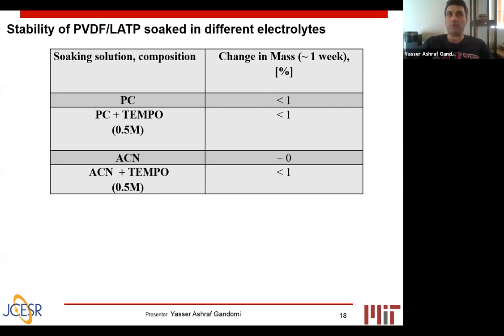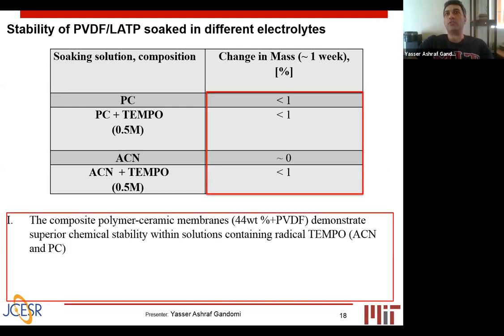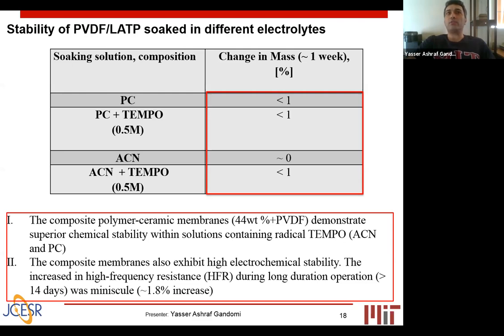So we did similar experiments. We soaked these composite membranes in the solution containing different solvents and also Tempo. And as you can see here, the loss in mass was negligible after a long duration soaking. And also I ran a long duration electrochemical impedance spectroscopy analysis where I recorded the high frequency resistance throughout different days, more than 14 days. And as you can see here, almost negligible increase in HFR was recorded, confirming a good mechanical and electrochemical stability.